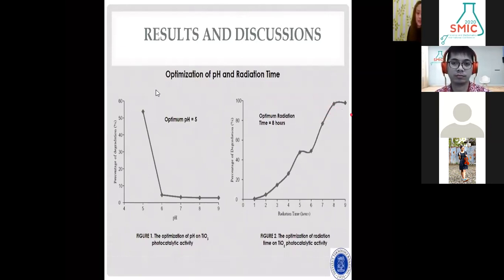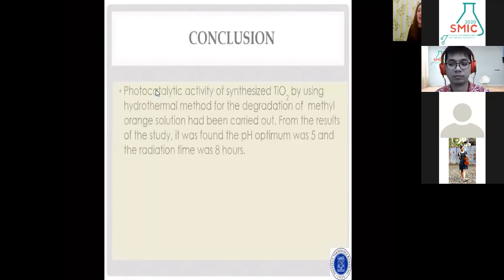This shows that between 1 to 8 hours of interaction between UV light, titanium dioxide, and methyl orange, the greater the degraded methyl orange. Physically, this could be seen from the change in the color of the solution from orange to colorless. So here is our conclusion.